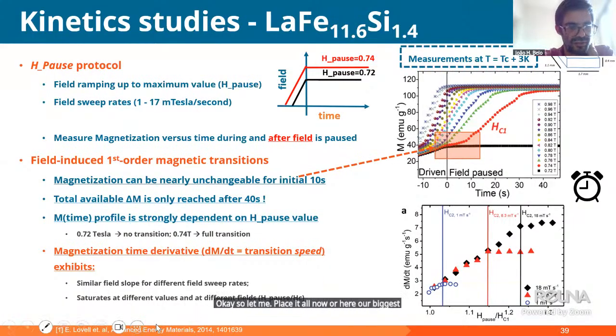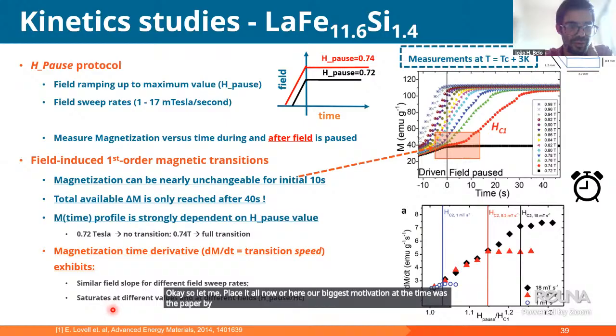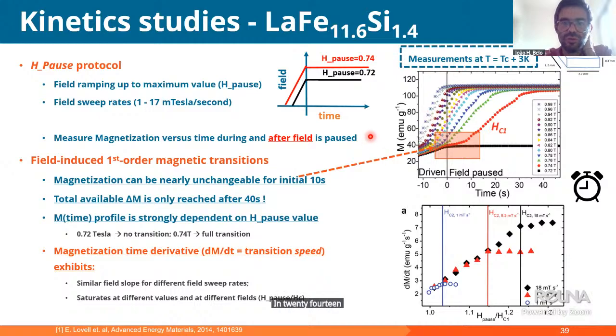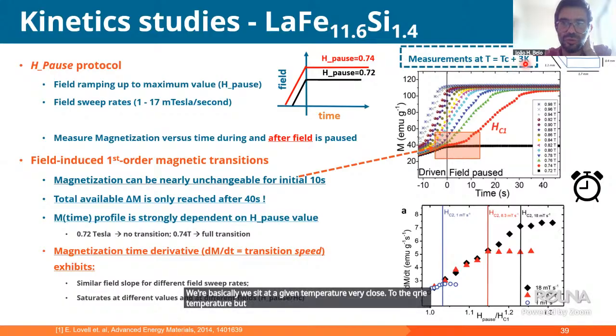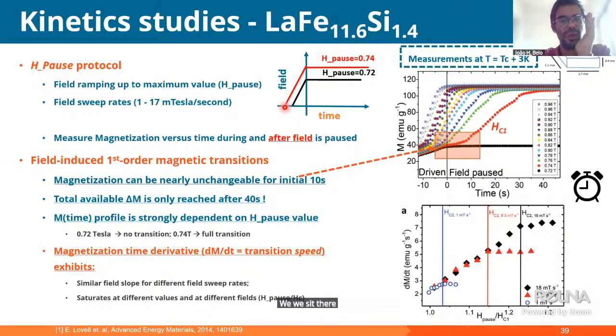Our biggest motivation at the time was the paper by Edmund Lovell from Imperial College in Advanced Energy Materials in 2014, where he did a very interesting experimental protocol, which became termed the H-pause protocol. Basically, we sit at a given temperature very close to the Curie temperature, but slightly above, in this case 3 Kelvin above. We sit there, very stable. We apply a magnetic field up to a given H-pause value, and this parameter can be changed, and then we just measure the magnetization as a function of time.